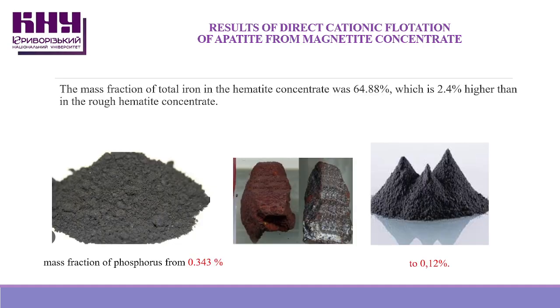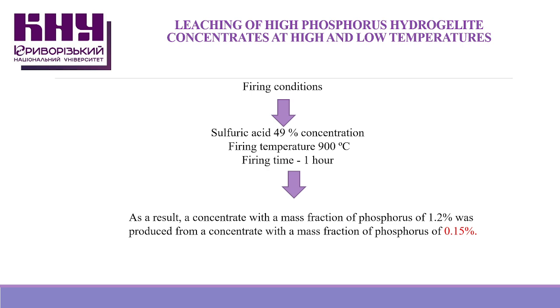As a result of a series of tests in hematite concentrate, it was possible to reduce the mass fraction of phosphorus from 0.343 to 0.12%. The mass fraction of total iron in hematite concentrate increased by 2.4% to 64.88%. In the third stage, the conditions for leaching poor hydroxide concentrates with high phosphorus content at high and low temperatures were analyzed.